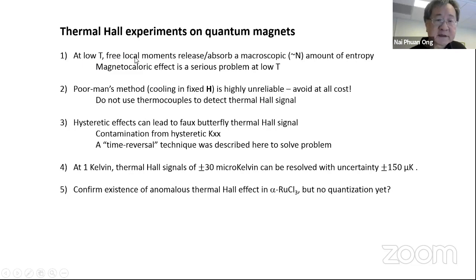At low temperatures, a paramagnet, a free local moment, has a huge amount of entropy. As I mentioned, I compared a thimble full of material to a 3-ton car made of solid copper. They share the same heat capacity. So that's a sobering thought, right?